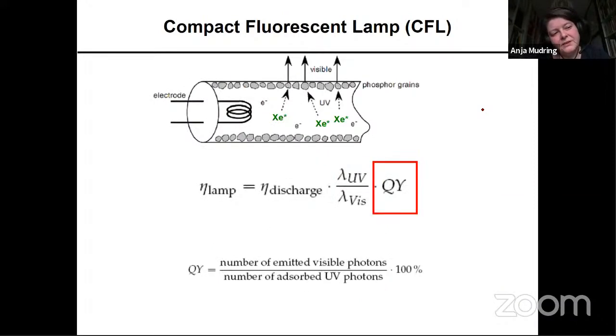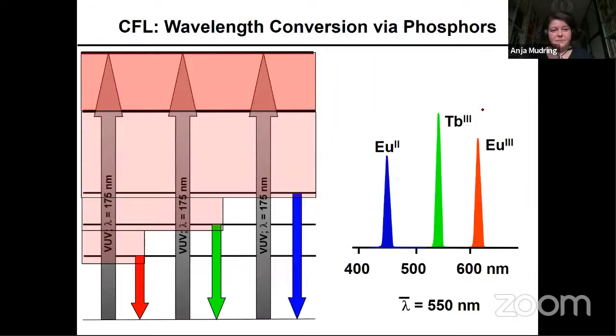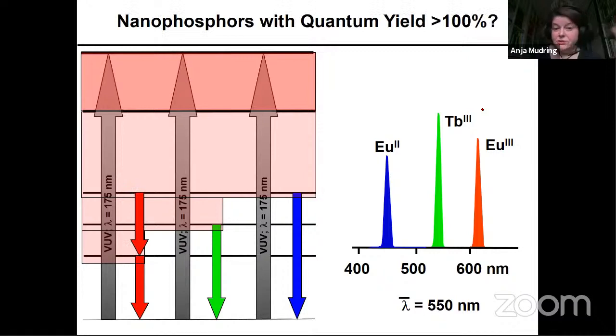Unless you start working at the last term in that equation, and that is the quantum yield or quantum efficiency, the number of emitted visible photons per absorbed UV photon. And if you could do the crazy thing of rendering this higher than 100%, so for example, when we go back and look at this diagram where we have this terrible red light problem, you see how little energy we're getting out compared to the energy that we're putting in. That should be sufficient to get out 2 red photons, which means a quantum efficiency of 200%, and rendering the whole concept environmentally benign and energy efficient.